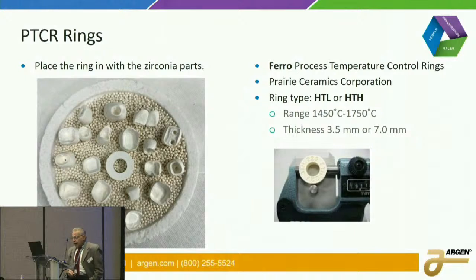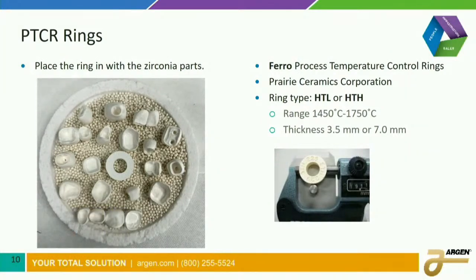One of the things we always recommend is for you to use a PTCR ring. And these are little rings made out of alumina. And this is the proper way of putting it in your tray. What you want to do is make sure that you put it in the tray with a full tray, because the zirconia does not pick up heat very fast, and neither does it release heat very fast. So you have to be careful. The temperature in the furnace is not going to be the temperature of the zirconia. So what does that mean? That means you can't run a PTCR ring by itself in the furnace. You have to use it with the work, because the zirconia is going to pick up some heat, which is going to be reflected in the PTCR ring.